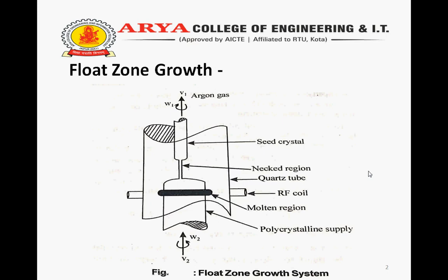There are four methods that can be used. First is core doping. Core doping refers to the use of a doped polysilicon rod for the starting material. On the top of this rod, additional undoped polysilicon is deposited until the average desired concentration is reached. This process can be repeated through several generations if necessary.